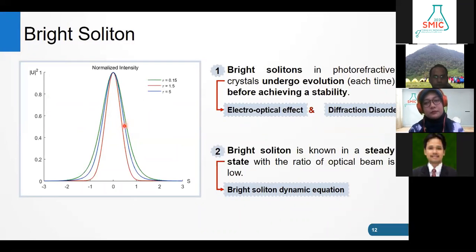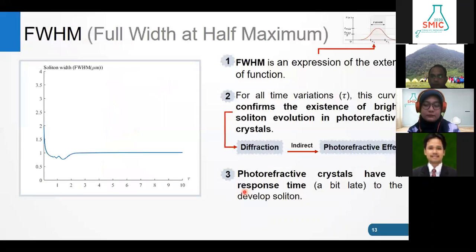We suggest that this is because of the electro-optical effect and diffraction disorder. And the bright soliton in this crystal is known to be in a steady state when the ratio of the optical beam is low. This statement comes from the mathematical formulation of the bright soliton dynamic equation.